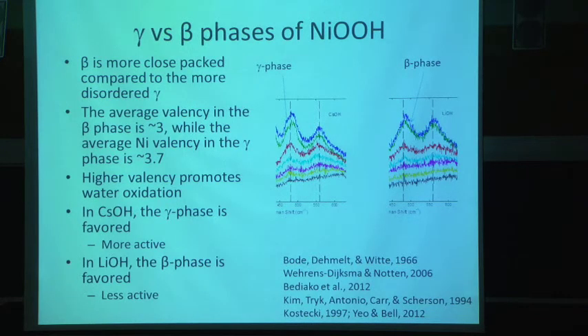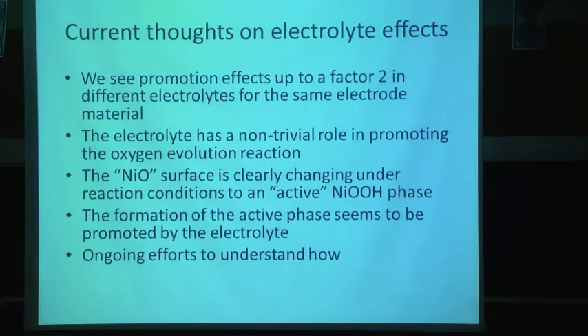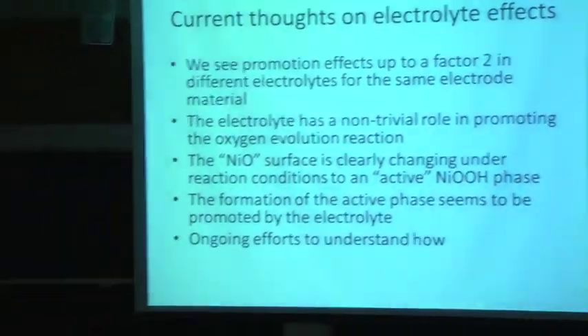So that's our current thoughts. We see some promotion effects up to a factor of 2 just by looking at different materials. We're currently going back to the nickel-iron system to try to assess whether that spinel phase may favor the formation of that gamma phase that we talked about. In any case, for nickel oxide, the electrolyte has a fairly non-trivial role in promoting oxygen evolution, and the surface is clearly changing under reaction conditions.